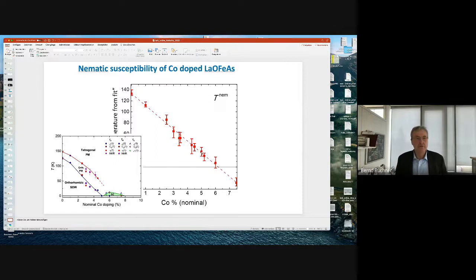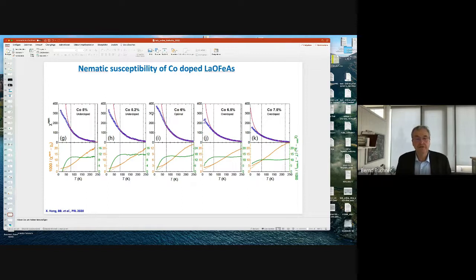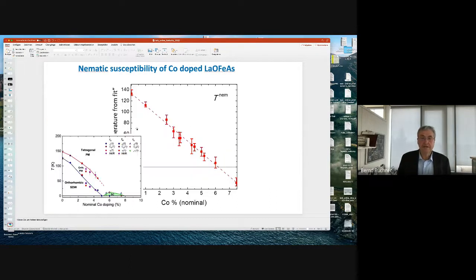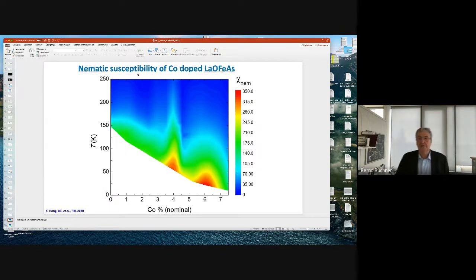You can do it also in a different way. If you go back to the last transparency, you can also simply have a look at the absolute values of this susceptibility. And you see, if you go to overdoping, this susceptibility becomes much smaller than it is at optimal doping. And even if you go to underdoping, it becomes smaller again. So if you simply take the absolute values of the nematic susceptibility and plot that as a function of the cobalt concentration, you really have a surprise. You really see two regions where this nematic susceptibility becomes huge, becomes very large.